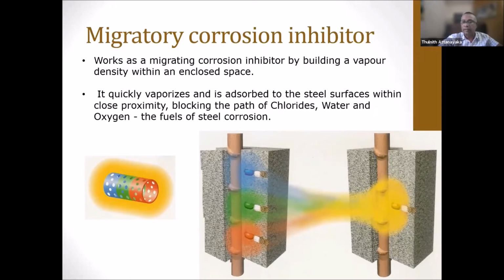So we have small capsules like this, which quickly vaporize inside the concrete, because we know that concrete is very porous. Porosity is there, and it absorbs onto the steel surface within close proximity. We normally insert one capsule per cubic meter, blocking the path of chlorides, water, and oxygen that fuel the steel corrosion. I mean, to reduce the corrosion, chloride, water, and oxygen are blocked from the path to the reinforcement bar.